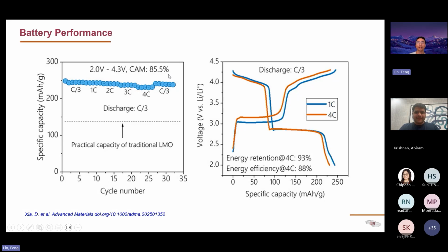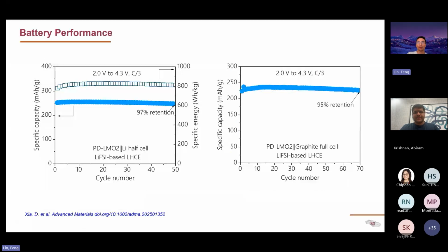We still get some conductivity problems with this material. Otherwise, we can go even much higher cathode active material. But you don't see a lot of rate penalty as you go for high C rate. The mass loading here is around 1.5 milliamp hour per centimeter square. And then long-term cycling showing encouraging result.